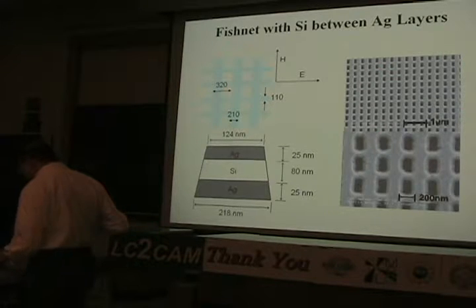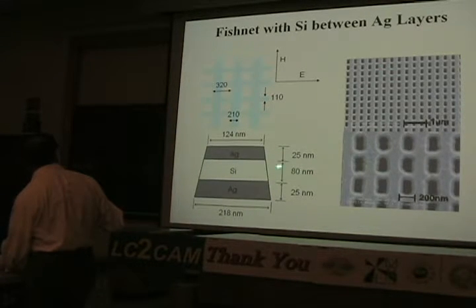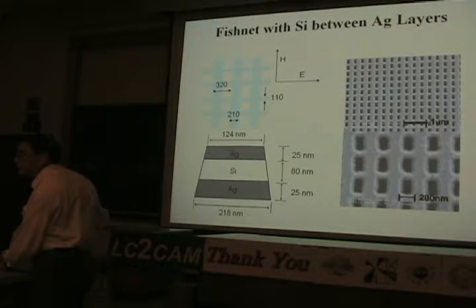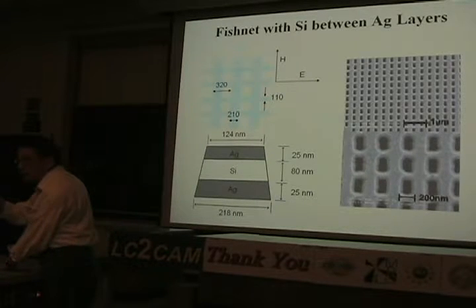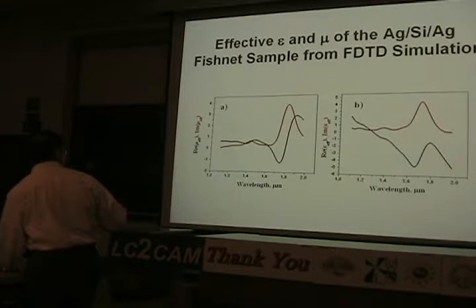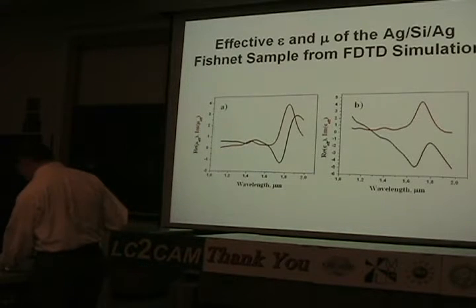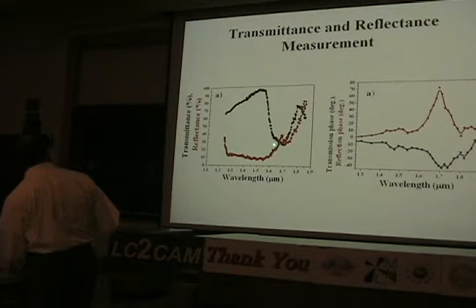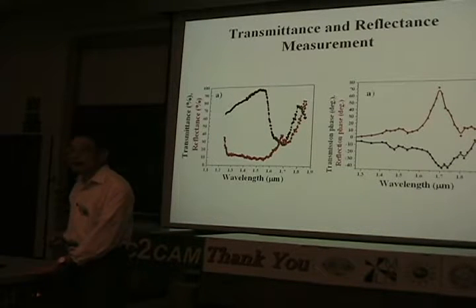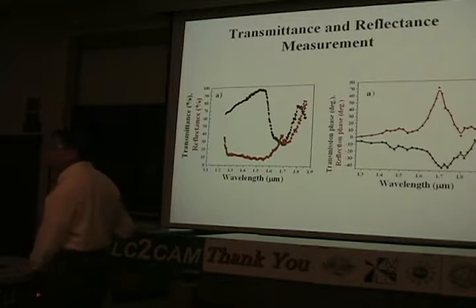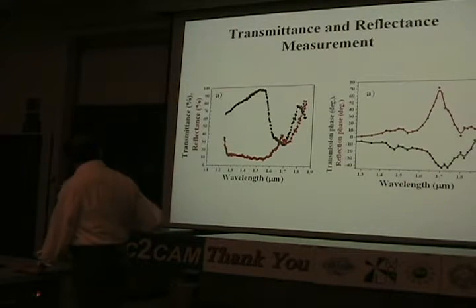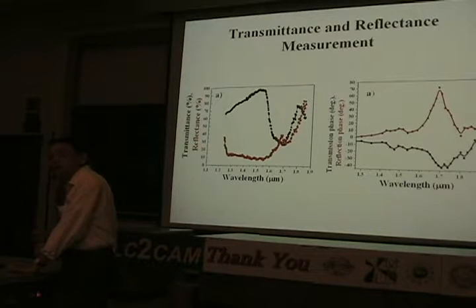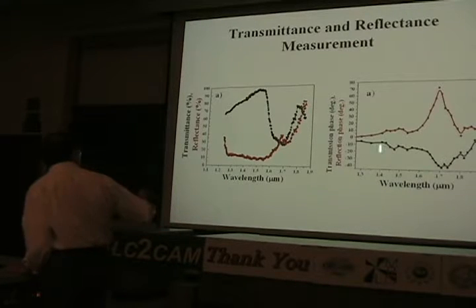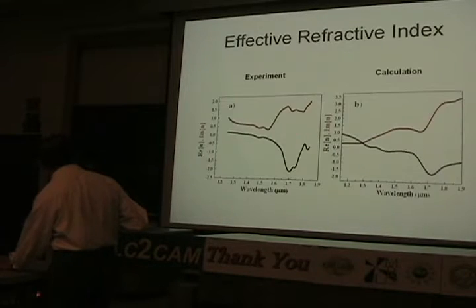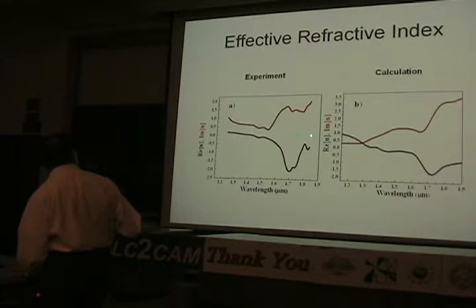So with that, again, the same pattern for the fishnet structure and so on, except that the dimension is slightly different, and that still gives us a resonance around 1.6, 1.7 micron. So this is the calculation, and the measurement again shows this dip in the transmission. Again, remember that the drop here is because epsilon less than 0, mu larger than 0. The rise here is because epsilon less than 0, mu less than 0. So the phase measurement is here, and from this we can again deduce the refractive index, and again you see that in this whole region the refractive index N is less than 0.